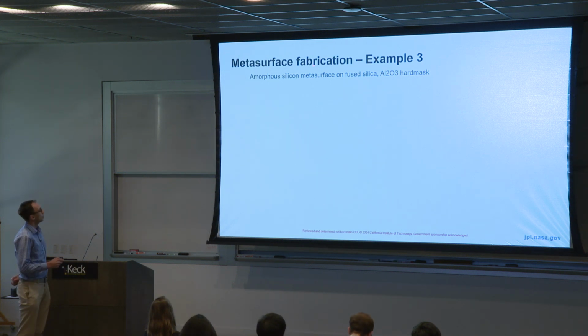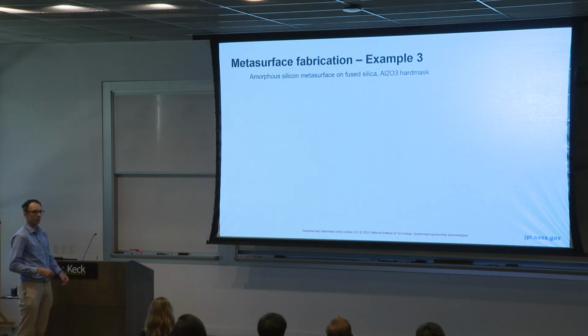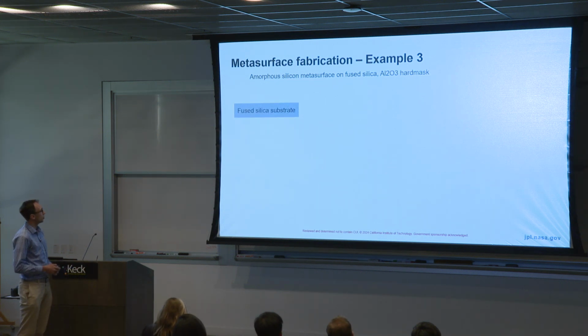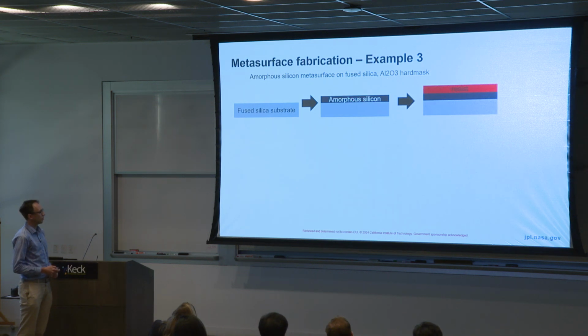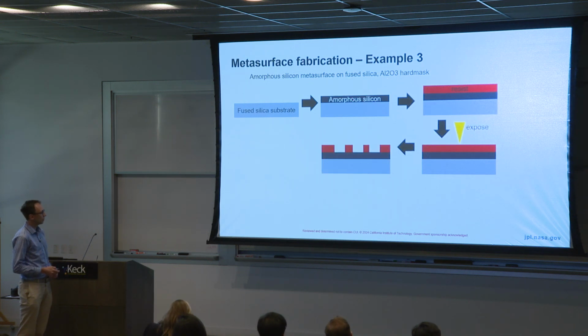I'll return to this in a second, but for the sake of argument, assume that you want to make use of these materials. You would want to make an amorphous silicon metasurface on a fused silica substrate. So you would start with what is essentially a glass wafer. You would deposit amorphous silicon, or you can even buy wafers pre-made with amorphous silicon deposited on top. You would spin coat resist, expose it, develop it, and now we're going to do something slightly different.